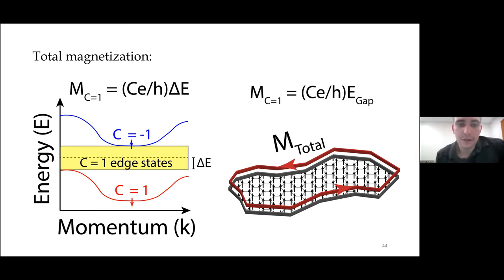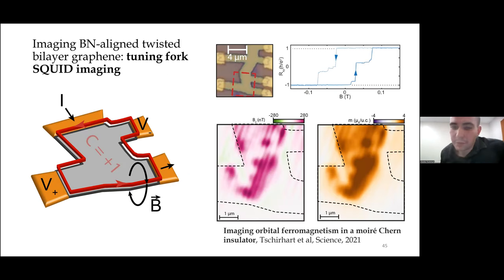Unlike a spin magnetization inside of an exchange gap, as you add electrons, as you change the chemical potential, you will be adding additional contributions to the magnetization because you will be adding electrons to a quantum state. And it's easy to calculate this contribution to the magnetization. It depends only on the Chern number, the size of the gap, and some physical constants. So this is something that we can probe directly with the SQUID. I'm not going to get too deep into this paper. You can read it right here. But the main point is that we can easily see in twisted bilayer graphene that this system is in kind of a unique limit in that the dominant source of magnetization is the chiral edge state. So the magnetization contributed by spin and the non-topological orbital magnetic moment is relatively small compared to the chiral edge state's contribution to the magnetization.